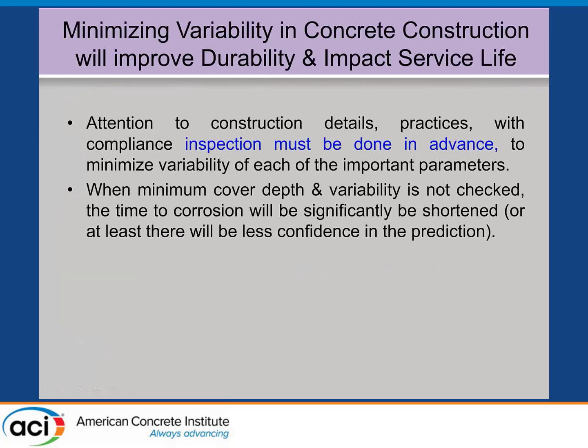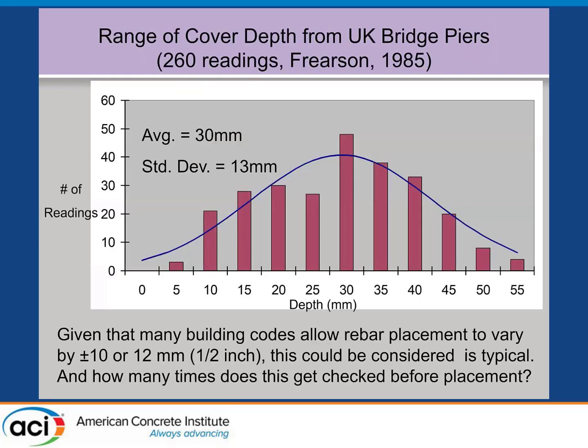You want to minimize variability, and you want to do that in advance, especially with things like cover. You can measure cover after the placement, but that's too late to do anything about it. What you'd like to do is measure it before. A lot of specs allow plus or minus half an inch on cover. This is some data from the UK showing a bunch of bridge columns. They had 30 millimeters cover, like an inch and a quarter, but the standard deviation is just over about half an inch, which means a whole bunch of the cover is down about a quarter of an inch, which isn't very good.